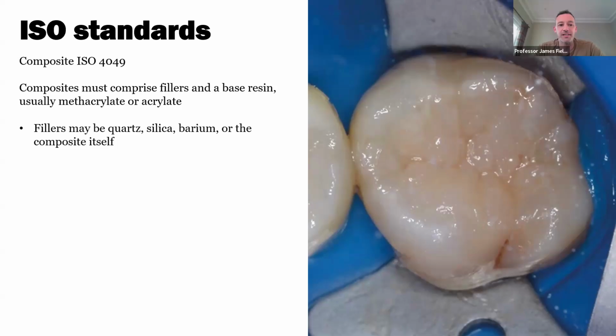Now, the fillers might be made of quartz, they may also be made of silica or barium, or like some of the Dentsply Sirona products now, and have been for a while, but the filler might actually be made of some of the cured composite itself, which actually is a very clever way of producing filler. And it's a way of ensuring that the filler remains better bound to the base resin, which reduces things like crack propagation and failures, kind of cohesive failures. But we'll talk much more about that in the subsequent webinars.